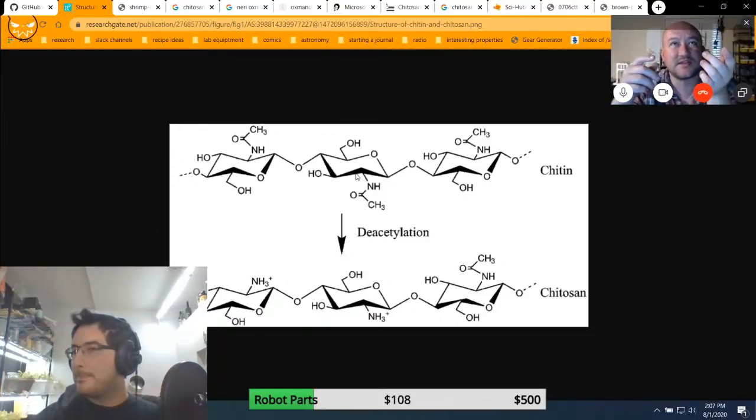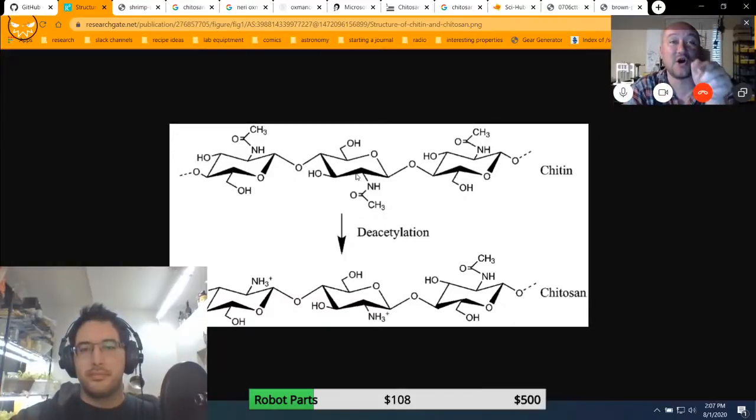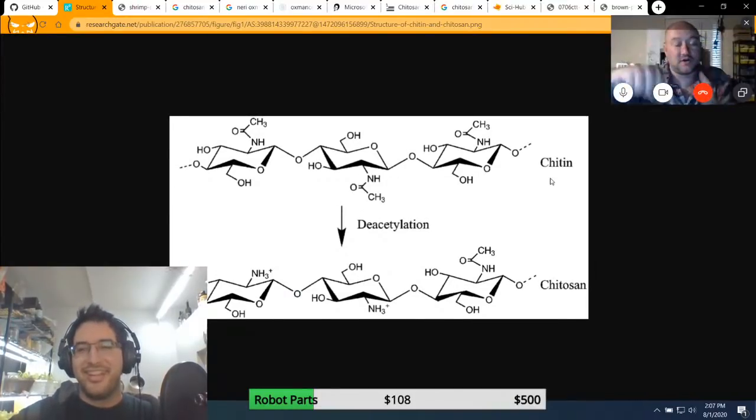It's 3% chitosan to vinegar, mass to volume ratio. That's the most you can get to dissolve initially. We tried stronger. I even bought 76% acetic acid. This stuff will burn a table. You need to wear a mask and goggles to handle it. It totally doesn't dissolve it more. You just need a little acid, so you can just take normal kitchen vinegar and mix it in.